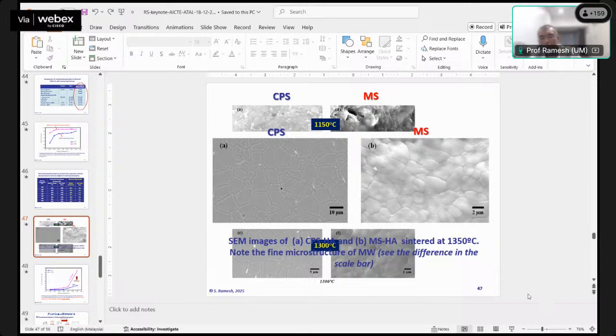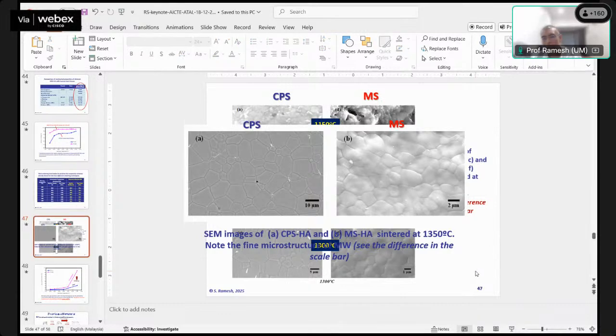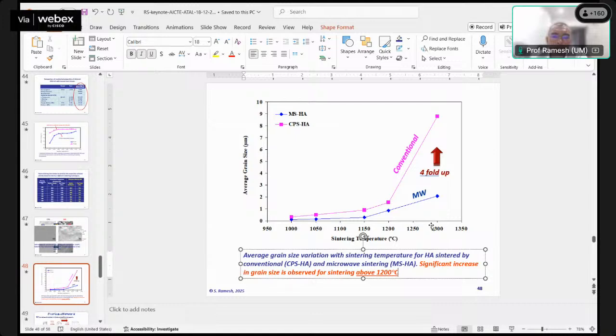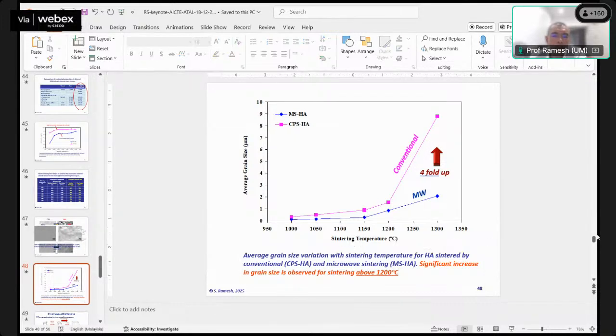So these are some figures on the microstructure, but because I can't show it in the PowerPoint mode, you are not able to see. But as you can see here, this is very large by conventional HA sintered. You can see 10 micron as compared to this 2 micron. They are at different magnification, but the scale tells you the difference in terms of the microstructure. So grain size wise, it is reduced by fourfold as compared to conventional when you compare at 1300. Okay.